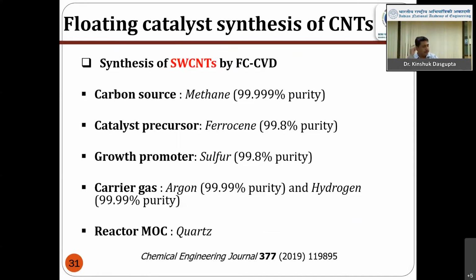Now, if I want to produce single wall carbon nanotube, that means only one wall is present, then the fluidized method generally does not give you single wall carbon nanotube. We need to go for a floating catalyst chemical vapor deposition, and a carbon source, methane, is used, because methane has one carbon, so it is easy to control the input of carbon by using methane. Other things are the same: ferrocene we take, argon we take.